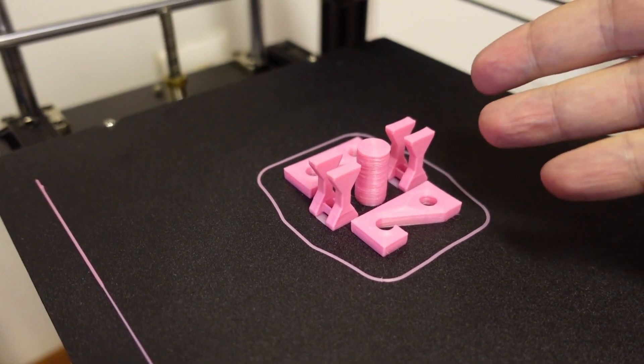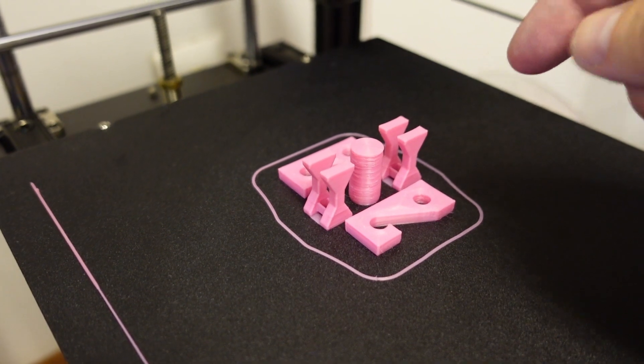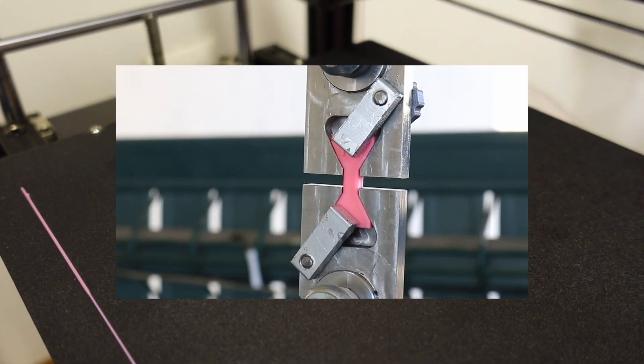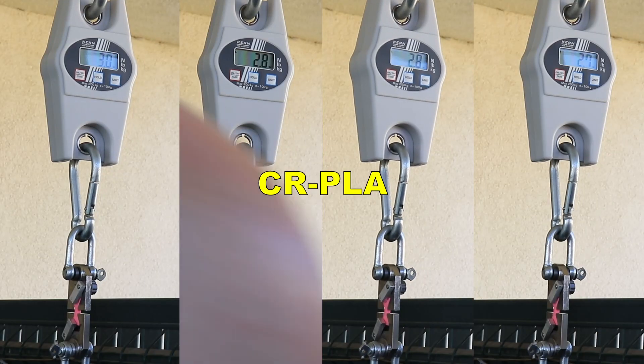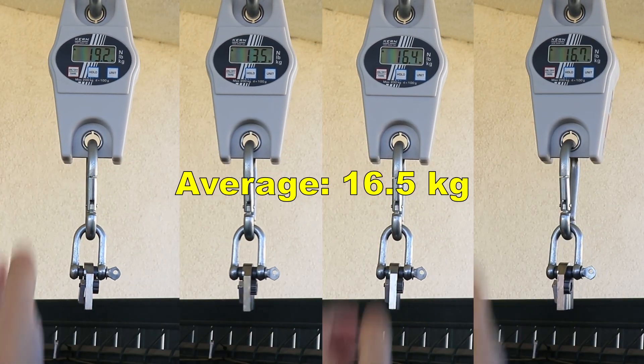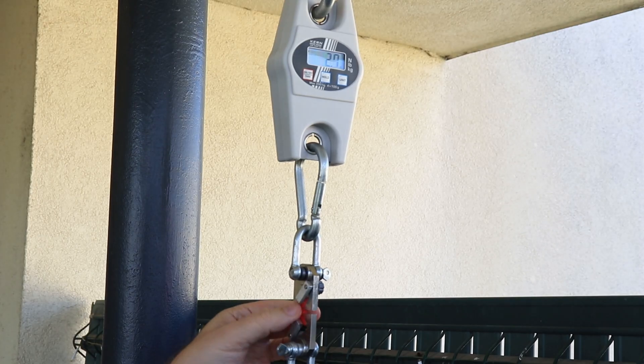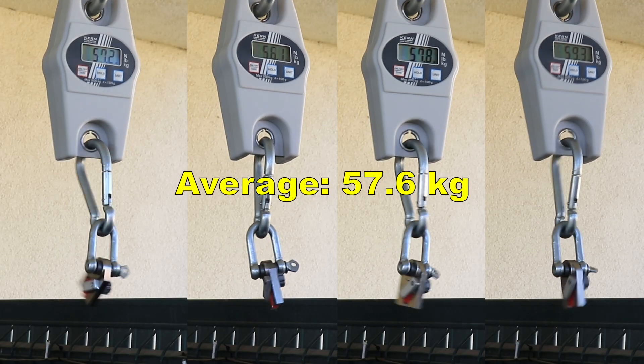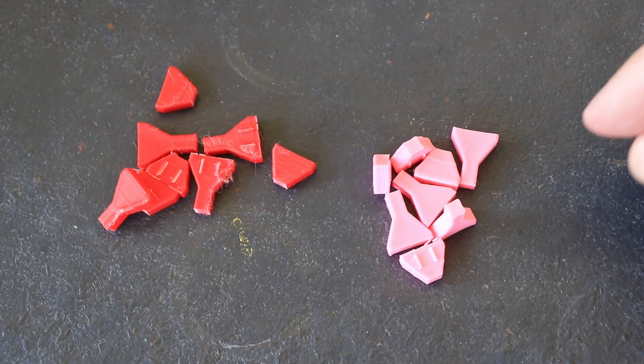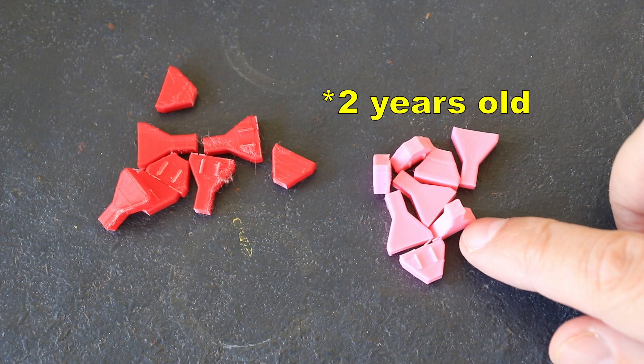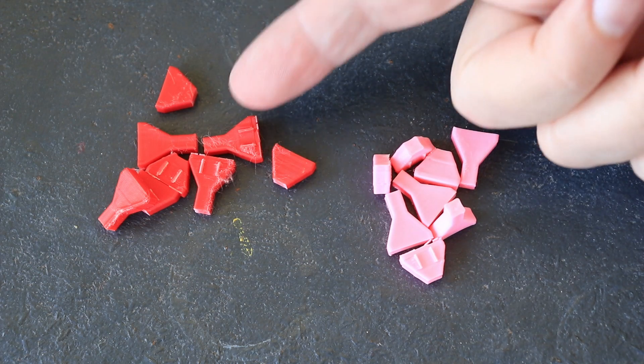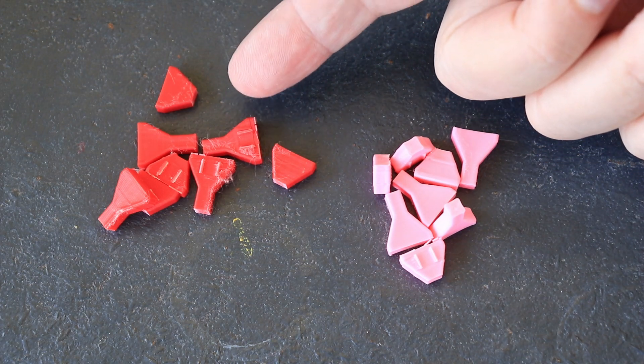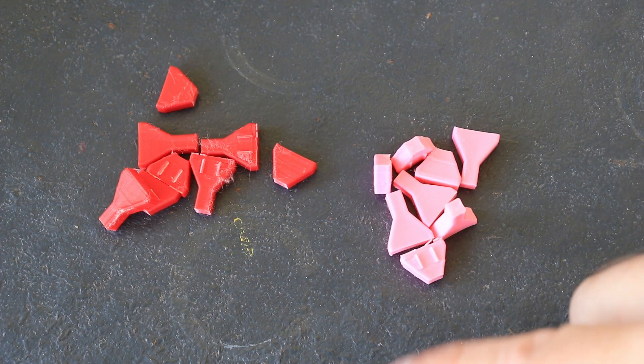I'm curious later if I will experience any difference in the layer adhesion. And it's finished. The object looks very similar like with the previous material, but I think it's time for the material testing and I will start with the layer adhesion test. So these are those vertically printed test objects for the layer adhesion and I'm starting with CR-PLA. Quite weak, below 20 kilograms. And now the Hyper PLA and this was very strong actually. Well the difference was very big.